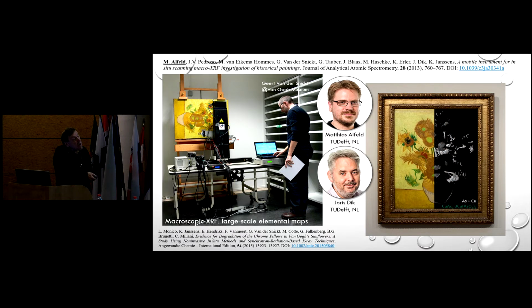So with these XRF maps, you can figure out, for instance, by looking at the arsenic and the copper distribution, that all the green here in this painting is made with a pigment called emerald green, where these two are together. You can look at where the mercury is that Van Gogh used to paint the darker yellow flowers. And of course, you can look at where the chromium is, etc., because that's a major metal in this very yellow painting.